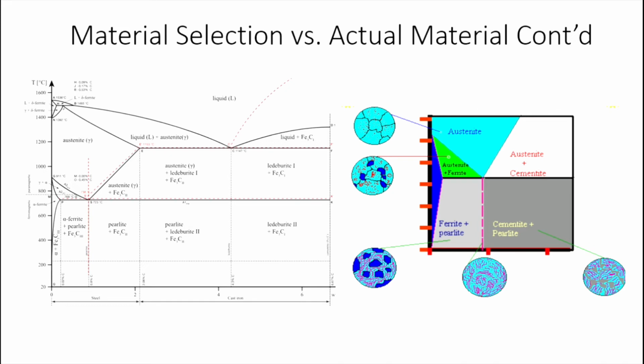During the cooling or tempering process, the 1080 steel has a carbon content that is very close to the eutectoid point, meaning a very pure pearlite structure is formed after equilibrium cooling. This pearlite structure strikes a balance between soft, ferrite-containing hypoeutectoid steel and harder, cementite-containing hypereutectoid steel. Although 1095 steel can be quenched and tempered to be tougher, harder, and stronger than 1080 steel, the extra quenching and annealing required to do this outweigh the benefits in the manufacturer's eyes.